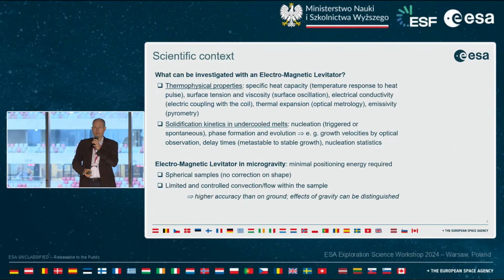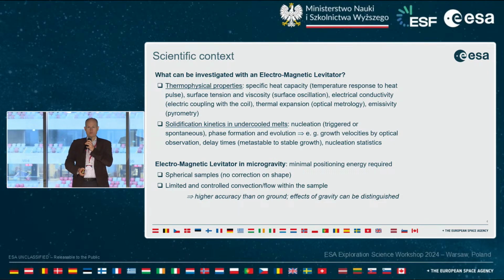And that's exactly the two types of science that you can do with the electromagnetic levitation facility. With the facility, it's possible to look into thermophysical property measurements of liquid metal alloys and semiconductors: specific heat capacity, surface tension, viscosity, electrical conductivity and thermal expansion, and also emissivity. And the second part is looking into solidification kinetics of undercooled melts, nucleation aspects, phase formation and evolution, so growth velocities, delay times between metastable and stable growth, nucleation statistics.